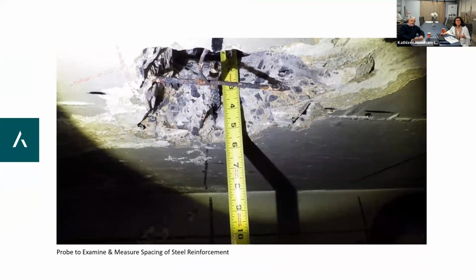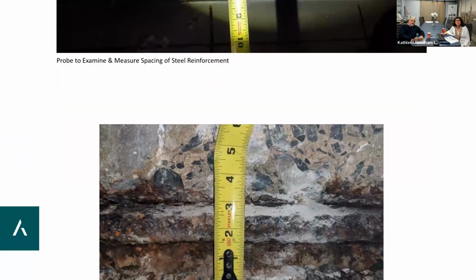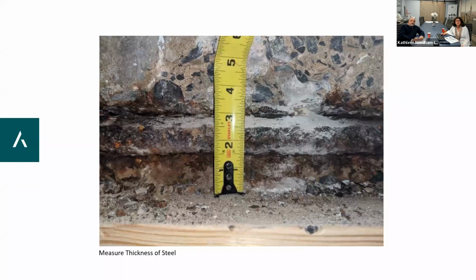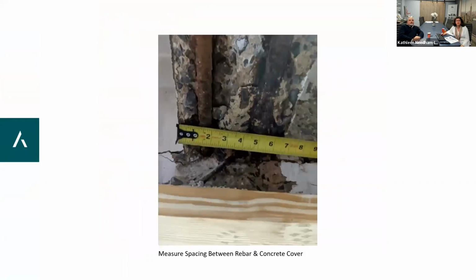And then we want to take a look at how much steel is left on the steel rebars. We want to measure the distance between the bars. That's very important for our structural stability analysis, as is measuring the thickness of steel members that we might encounter. So you see, it's also quite destructive. While we're doing the scan, we also have to open up the concrete to verify what the sizes are once we know where the rebar is located.